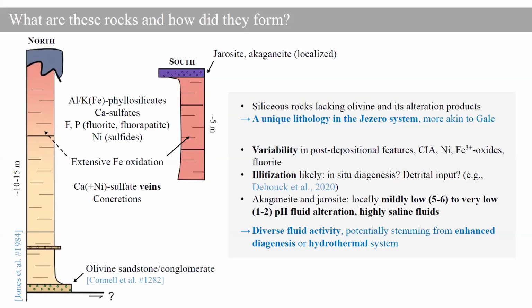And so we think that we see some extensive overprint of diagenesis and fluid circulation. And that possibly includes some hydrothermal processes, because we are seeing fluorite as well, which on Earth is more often associated with hot fluids. We also have indication of illite, so a typical mineral formed during burial and diagenesis. But here it's unclear if we are seeing processes that happened in situ or in the watershed instead. So finally, the upper part of the formation is associated with akaganeite and jarosite, which record low pH and saline fluids, perhaps due to exhumation and oxidation of the bedrock.